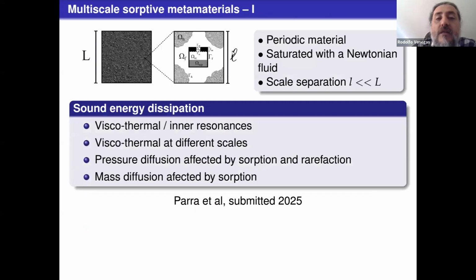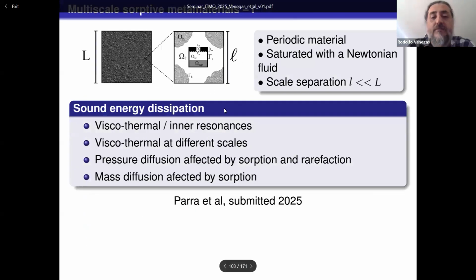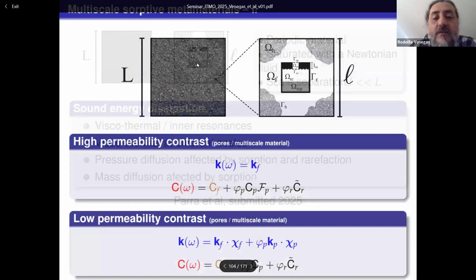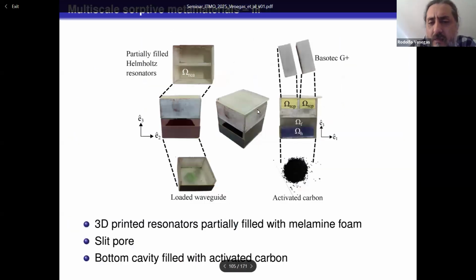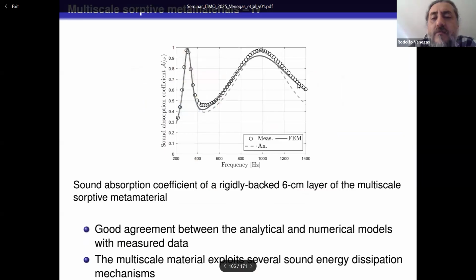So finally, multiscale sorptive metamaterials. This is a paper we've submitted recently, and it's a combination of activated carbons with some resonators with foams in it. So this is a realization of the sample, and here we can see that the analytical model and numerical model give very similar results to the measured ones. So there's a good agreement between the analytical and numerical models, and the multiscale material exploits several sound energy dissipation mechanisms.